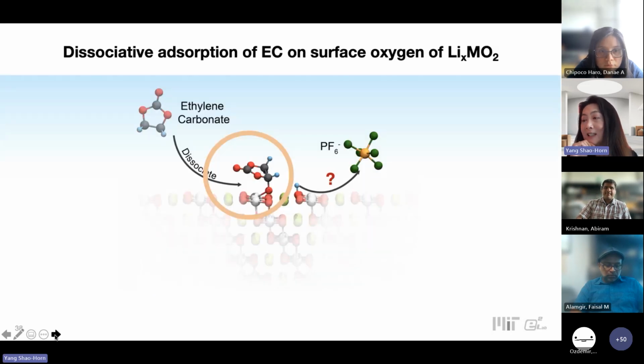So looking at the challenges of, let's say, nickel-rich positive electrode material, as we increase nickel to NMC 811, the cycle life of such batteries decreases significantly relative to NMC 111. And over the past decade or so, we've been working utilizing a combination of techniques, in-situ measurement, DFT, connecting the concept in catalysis applied to battery interfaces. And then we developed the following understanding and explain why the known carbonate electrolyte degrades on nickel surfaces.